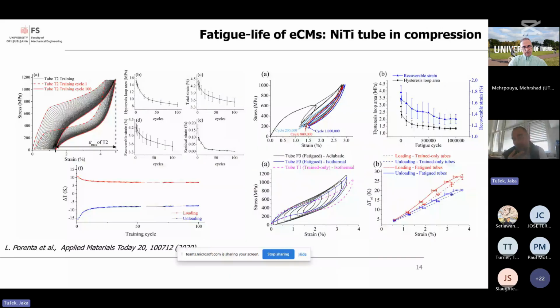So after training, we subjected a couple of tubes to fatigue testing, and over almost the entire transformation plateau, all the tubes survived. The tubes were stable enough, without buckling, which is a precondition, of course, for functional operation. And if they are stable, they don't show any structural fatigue up to 1 million cycles. What was even more important and, let's say, optimistic is that there was no functional fatigue either, because when comparing only trained and fatigued tubes, the elastocaloric effect was almost identical, which indicates that after the training, there's no degradation of the elastocaloric effect, which is again crucial for elastocaloric devices.